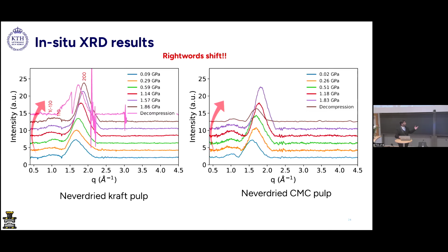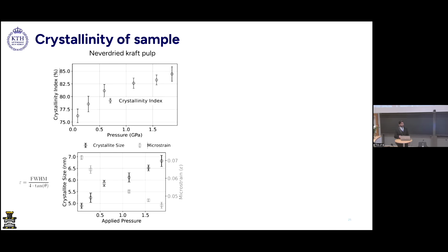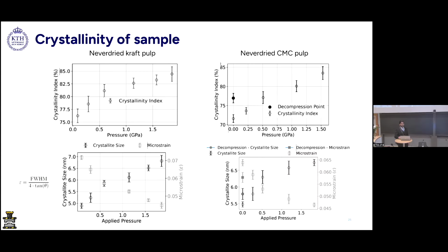And we wanted to quantify all of that. So we wanted to see how the crystallinity is changing, since in the literature we have seen changes in the crystallinity. For never-dried kraft pulp, we saw a gradual increase in the crystallinity with the incremental application of pressure. Also, the crystallite size was getting bigger. That could relate to co-crystallization. Also, when you have a slightly more ordered structure, the lattice microstrain should go down, which, when we calculated it, was correlating and going down.